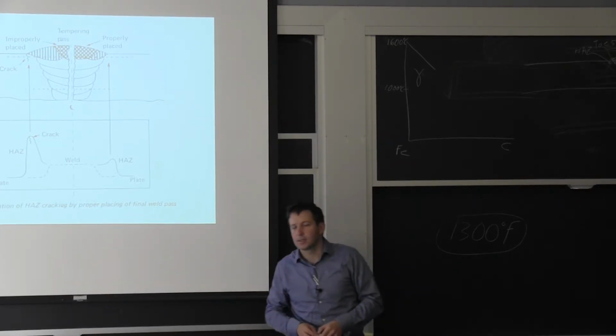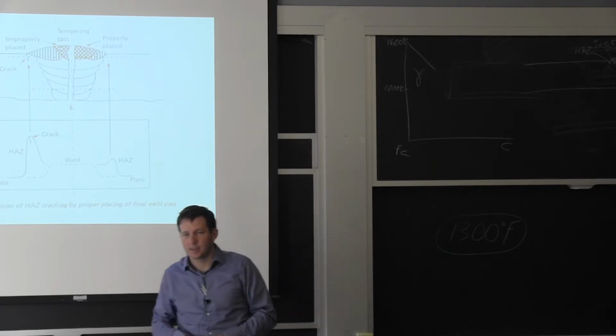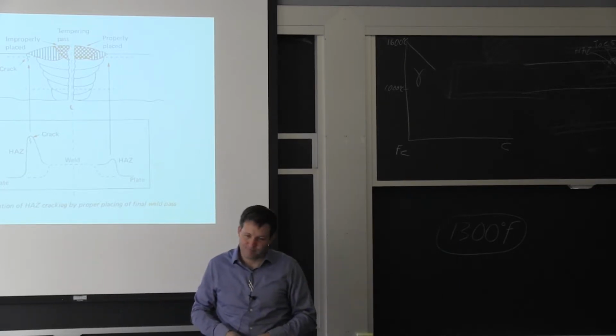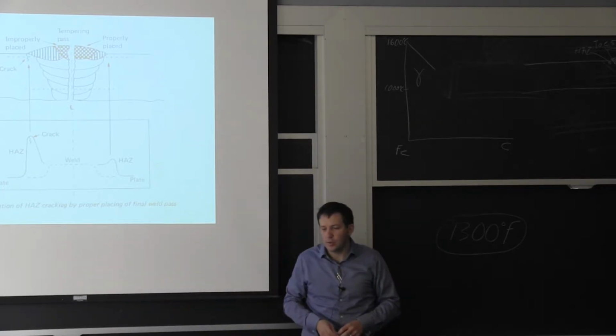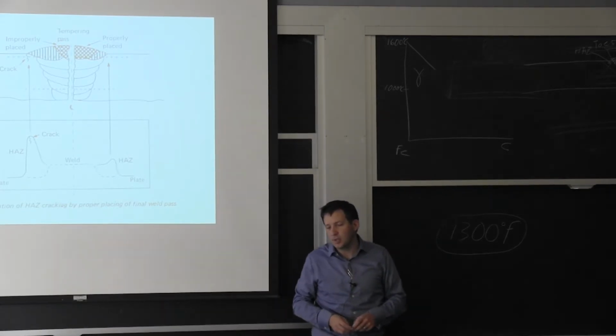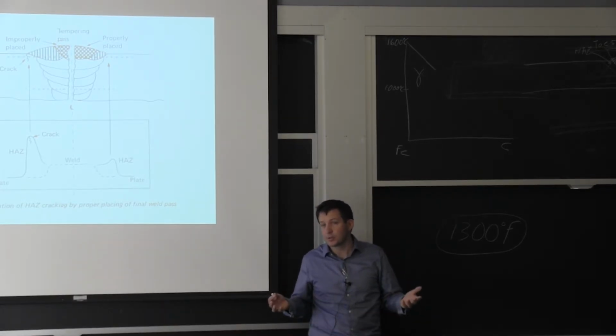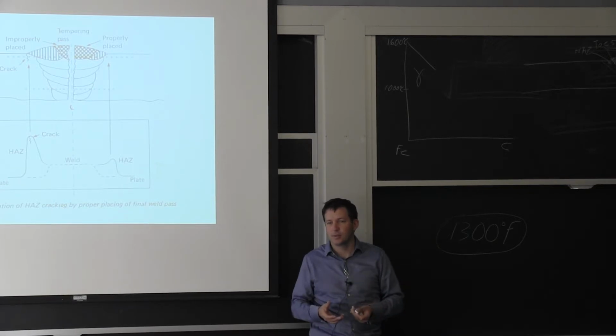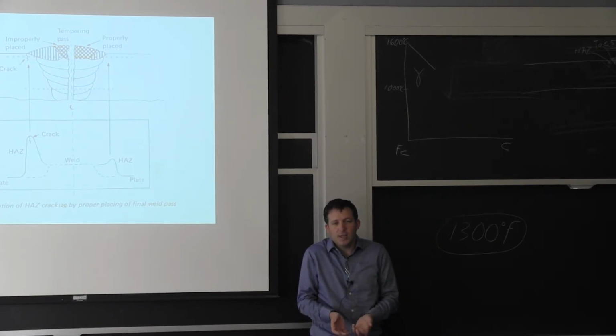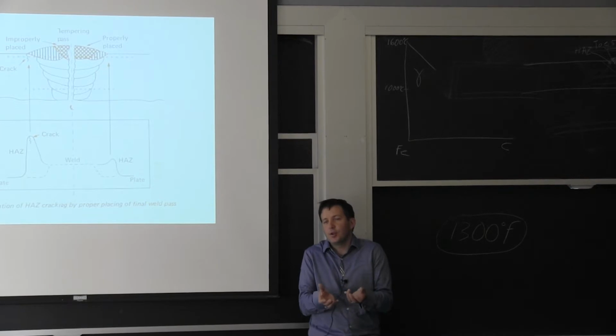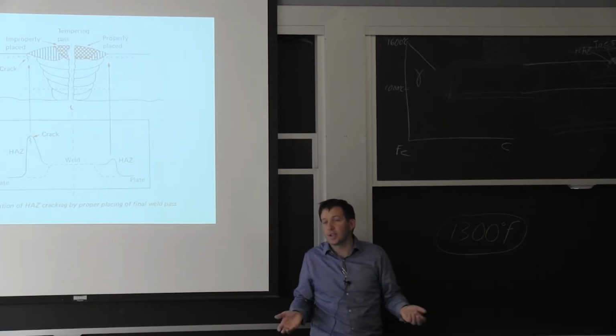Yes? How do you do those treatments on large structures? You can't stick the whole thing in an oven. Yeah, that's right. So if you're going to do a post-weld heat treatment, typically you come with torches and you locally heat the surface. And because now you're heating it all the way through the thickness, you don't mind when you're done just letting it go, because it will cool down very slowly.